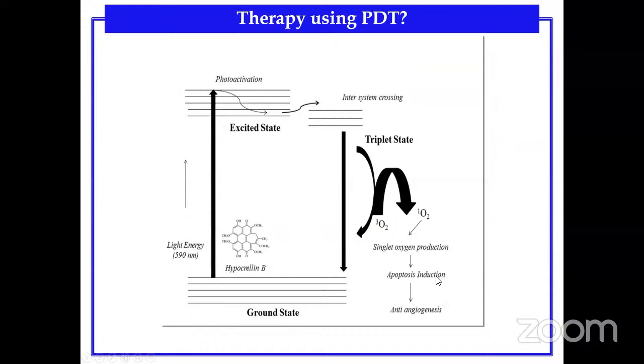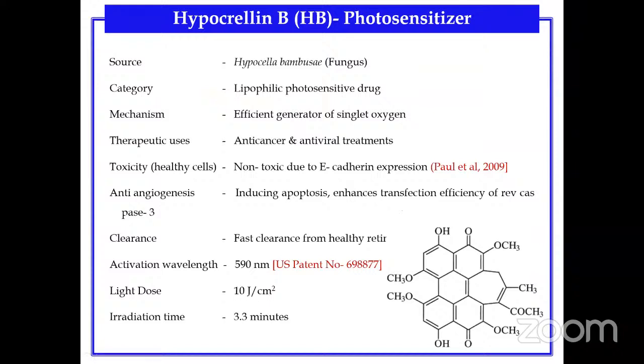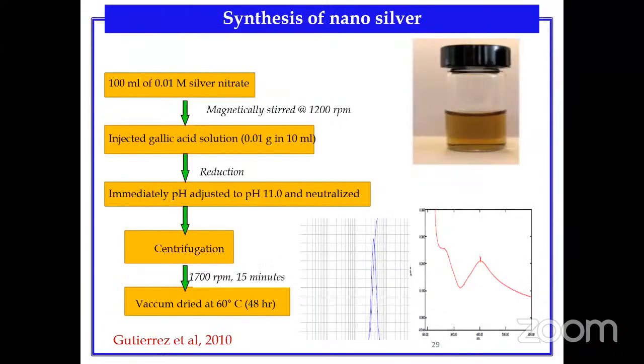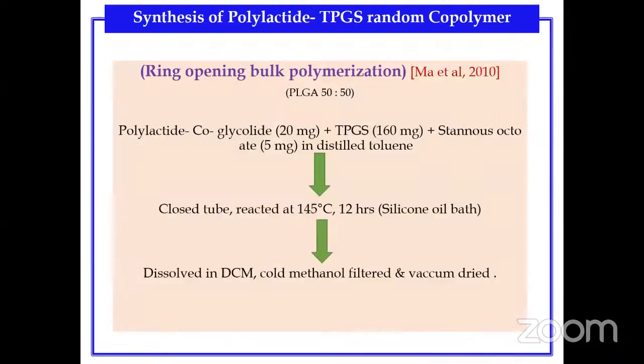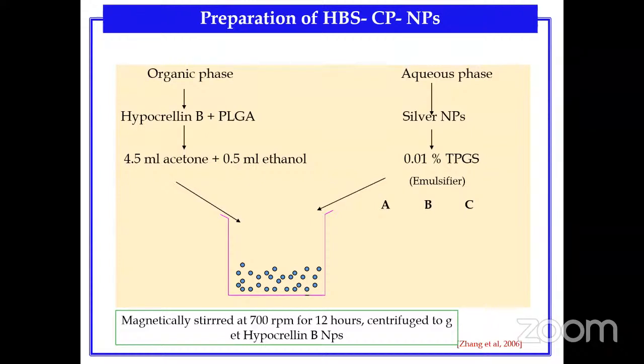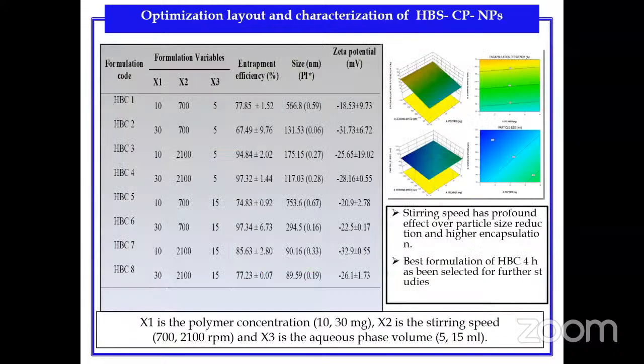That singlet oxygen induces apoptosis, which in turn will have that anti-angiogenesis effect, for which we have initially produced silver, and then we have also produced PLGA-TPGS random copolymers by ring opening polymerization techniques, which have been utilized to make nanoparticles loaded with a photosensitizer, and that formulation has been optimized by using design of experiments, wherein we have considered three formulation variables and response variables